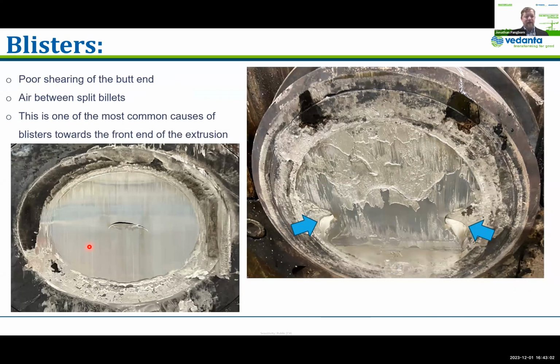Here are some examples of shearing. This is, I would say, a classic poor shear that is not well aligned, probably because the equipment is old in this case. It's hard to align it without it hitting the top of the die. It's really scarring the surface, and then you can actually see a little bit, where these arrows indicate, that metal is pulling out of a pocket going into a hollow, and there's going to be some blisters associated with that. And this is a quite special case where the shear actually looks generally pretty good, except there's a pull out right in the middle, and this is very deep.